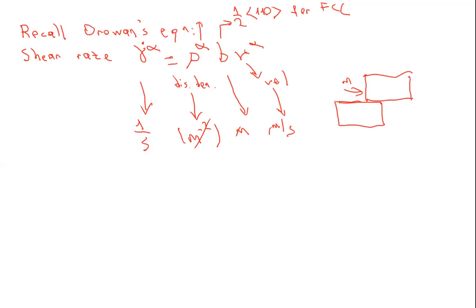So how can we calculate these values? Let's start with dislocation density. Dislocation density at each slip system. So dislocation density, actually it changes as the deformation takes place, right? During the deformation, the dislocation density evolves. And instead of calculating the dislocation density, I want to calculate the derivative of dislocation density. So this dot represents the derivative with respect to time, because the dislocation density changes with respect to time.